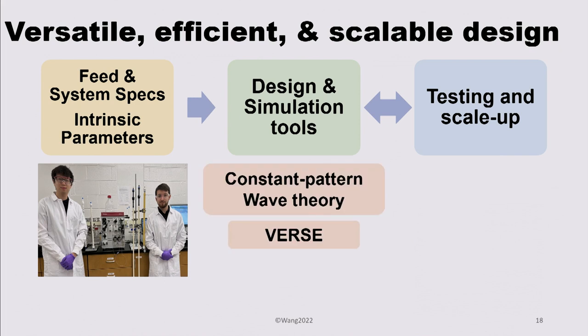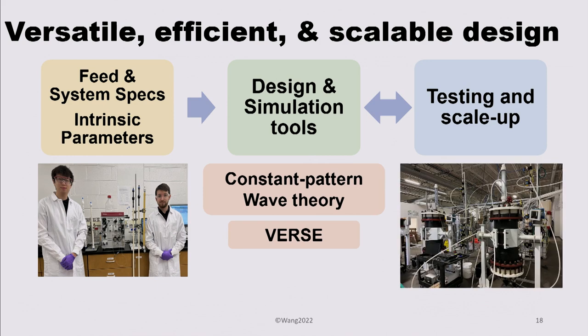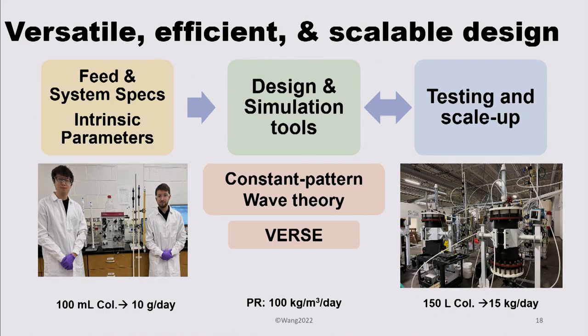up to test it. And so in this example, we have the 100 mL columns, and this scaled up to 150 liter columns, which is over 1,000 times. And the productivity, you can go from 10 grams per day to 15 kilograms per day in one column in the pilot scale.